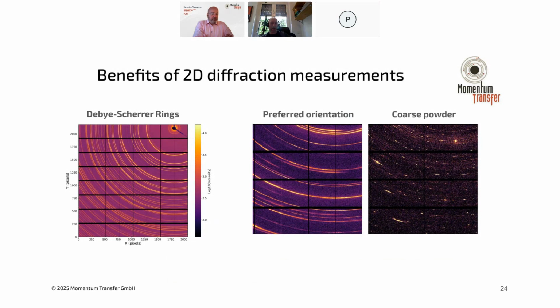And as you go out radially from that, going to sort of the lower left-hand side, you have these rings. And these are Debye-Scherrer rings that are the diffraction rings from the different lattice spacings in the phases of your sample. And so if you have a point detector, you're only kind of collecting one slice of that. And if you have a PSD, a position-sensitive detector, you're collecting a slice with a little bit of thickness to it. So you only collect sort of like a line scan in the radial direction. But with the area detector, you collect a much larger arc of these rings, and that allows you to look at this image and actually determine the quality of those rings.